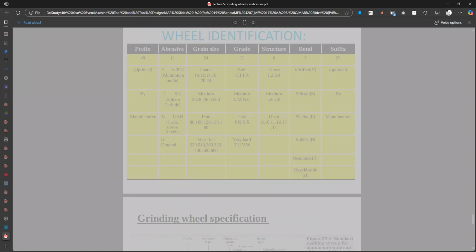Wheel identification. Prefix, abrasive, grain size, grade, structure, bond, suffix, e.g. 45 C 54 H 6 S 23, optional. A, Al2O3, aluminium oxide; coarse 10, 12, 14, 16, 20, 24; soft H, I, J, K; dense 1, 2, 3, 4; vitrified V; optional by manufacturer. C, silicon carbide; medium 30, 36, 46, 54, 60; medium L, M, N, O; medium 5, 6, 7, 8; silicate S. CBN, cubic boron nitride; fine 80, 100, 120, 150, 180; hard P, Q, R, S; open 9, 10, 11, 12, 13, 14; shellac E. D, diamond; very fine 220, 240, 280, 320, 400, 500, 600; very hard T, U, V, W; rubber R; resinoid B; oxychloride O.